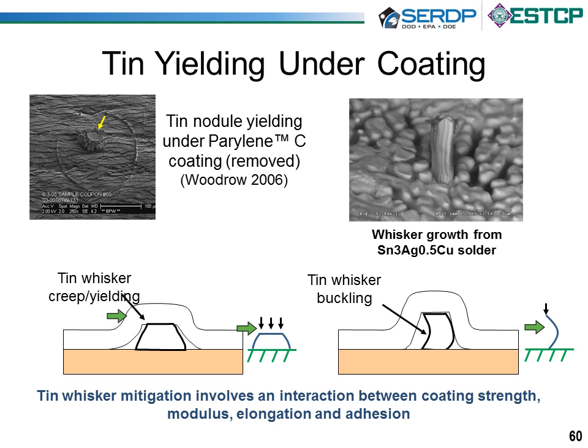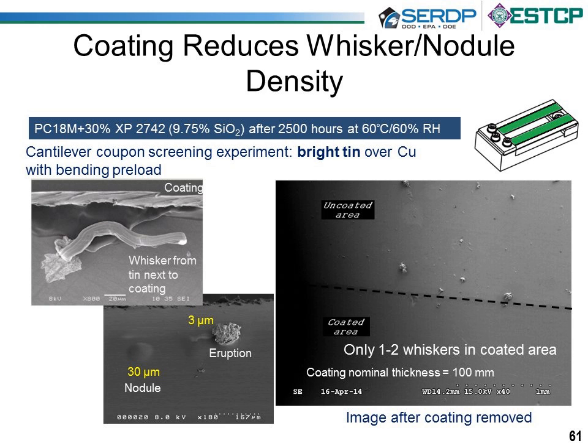So those are some of the things we're looking at to try to understand this interaction between the coating, its strength, its modulus, its elongation, and adhesion, and trying to find an optimal combination of those that give us favorable whisker protection. So some initial results of a coating. We did 2,500 hours of 60 degrees C, 60% relative humidity. Bright tin is a good whisker grower over copper. We did a little bit of bending preload. And interesting results. So that's like 3.5 months of testing. These are long, long tests to run.